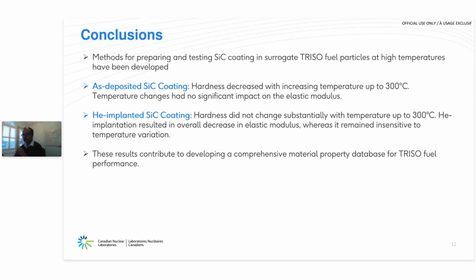And for helium implanted coatings, hardness did not change substantially with temperature up to 300 degrees centigrade. And overall elastic modulus for these helium implanted samples compared to the as deposited coatings was lower, but again it was insensitive to the probe temperature range. And these results are part of the effort to contribute to developing a comprehensive material property data set for TRISO fuel performance or for modeling purposes itself.